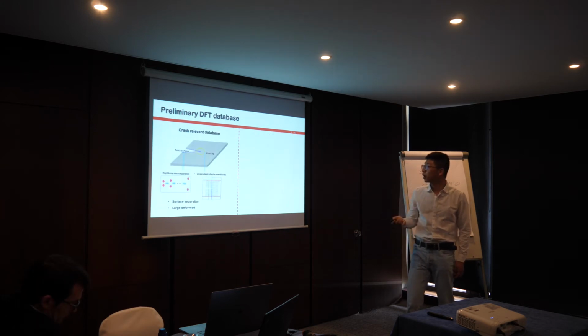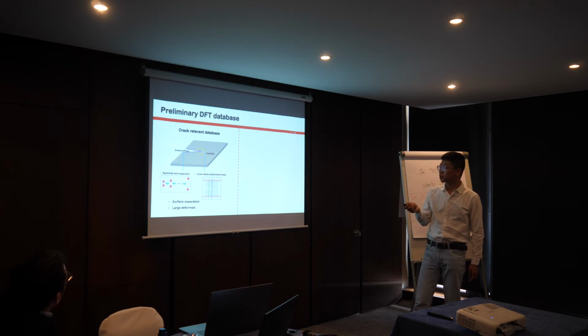So to enable the prediction of fracture, we enrich the database by adding more data. The first thing that comes to mind is that we can include some crack-relevant data. Imagine if a crack wants to propagate, it involves the separation of surfaces. Also, we calculate the strain field ahead of the crack tip to include the strain space of those atoms.